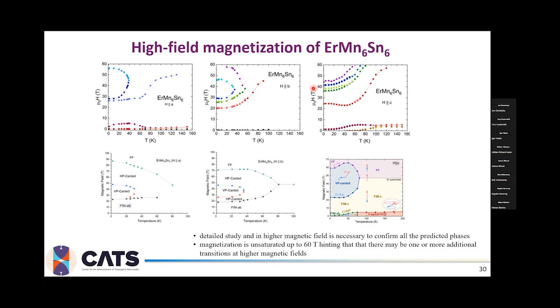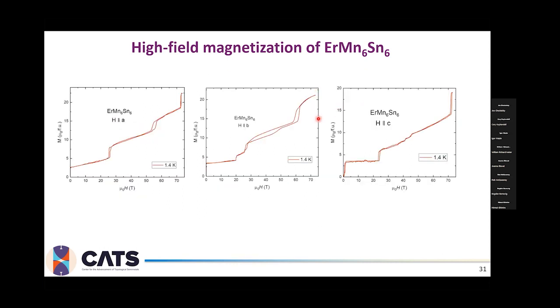And with that, that was our motivation to try even higher magnetic field and go to the 73 Tesla duplex magnet. Here I would like to show some of the curves collected at the low temperature, 1.4 Kelvin. With the magnetic field applied along the A direction, we can see all the transitions which I showed earlier. And indeed, we see one more, at 72.5 Tesla, which is literally at the limit of our duplex magnet, and it does saturate above that transition.